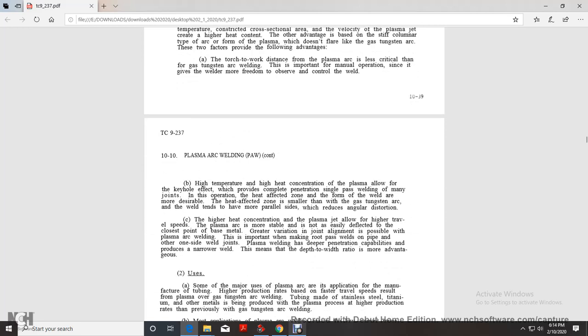For many joints, the high heat concentration makes the heat affected zone and the form of the welded area more desirable. The heat affected zone is smaller than with gas tungsten arc, and the weld tends to have more parallel sides with reduced angular distortion.